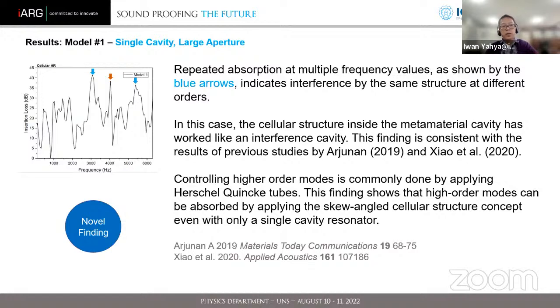The second one, repeated absorption of multiple frequency values, indicates that the absorption is induced by the same structure, but at different frequencies. So first resonance, second resonance, first mode, second mode, third mode, fourth mode, like that. This indicates our technology is working very well and successfully absorbs the energy of higher order modes of the sound wave. Absorbing more than one frequency with a single resonator is not provided by Helmholtz resonators or any other resonator structure available now in the literature. So this is a very, very novel finding.